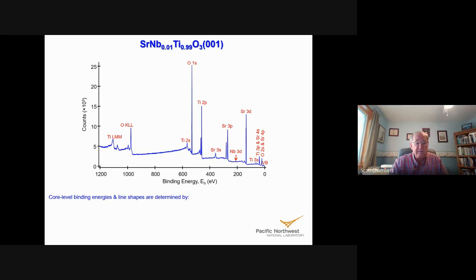And so there are really 5 different drivers for binding energies and line shapes. And what they are, first of all, the best known one is that of charge distribution or chemical environment. This is the one that pretty much everybody knows about. But another one that hardly anybody knows about is total electrostatic potential. And this can vary in semiconductors in some very big ways. And I'll talk about that toward the end of the talk.